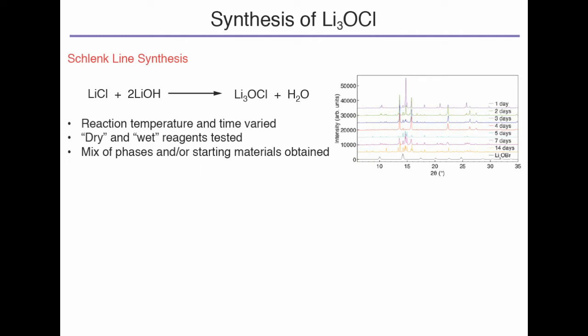So the first thing we wanted to do was to just try and reproduce what that paper had produced in 2012. So to do that, we tried to make this Li3OCl. It's a fairly simple reaction, or the concept's fairly simple. You have to do everything under inert atmosphere, so you have to do it under vacuum. The actual principle is that you take the very cheap starter materials, which are lithium chloride and lithium hydroxide, you heat the mass up past the point that they melt, and then when they melt, the idea is that the Li3OCl should just crystallize out like a perfect